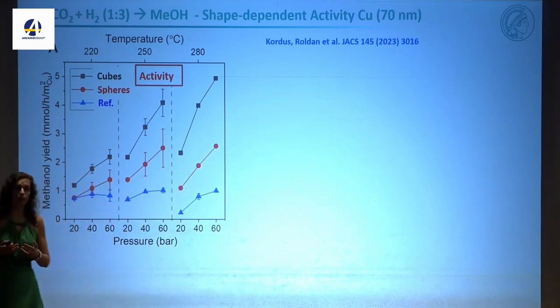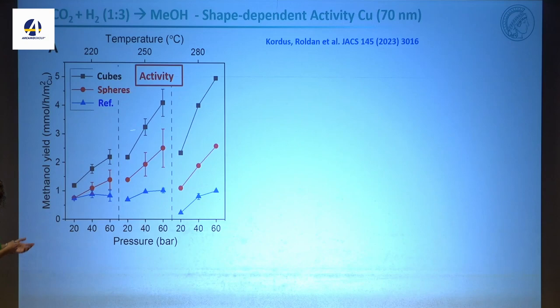Again, I compared 3 samples. I have the commercial catalyst that we bought. This is Alfa Aesar. Then we have copper spheres, same size, and then we have our oxide cubes. And if you look at the methanol yield, the cubes at all pressures and all temperatures that we investigated, they are always performing better. So they are more active than the same size spherical particles and than the commercial catalyst.